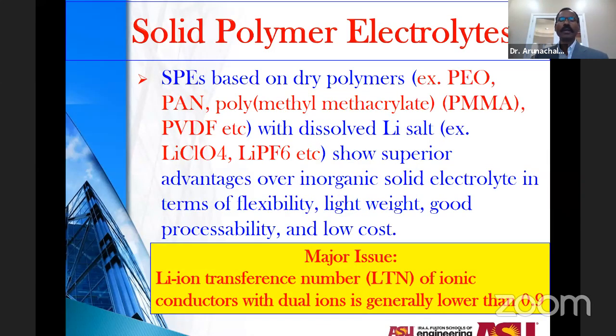So solid electrolytes mostly come from polymer electrolytes, as I just mentioned. In the solid polymer electrolytes, you can have PEO, PAN, or PMMA, or PVDF with lithium salts like perchlorate or hexafluorophosphate that can have good lithium-ion conductivity, again compared to solid electrolytes with inorganic materials. In addition, because it's a polymer, it can also lead to a little bit of flexibility, and certainly the density is lower for these polymers, so you can have a lightweight material. And because these are polymers, you can have better processability, and these materials can also lead to slightly lower cost also.